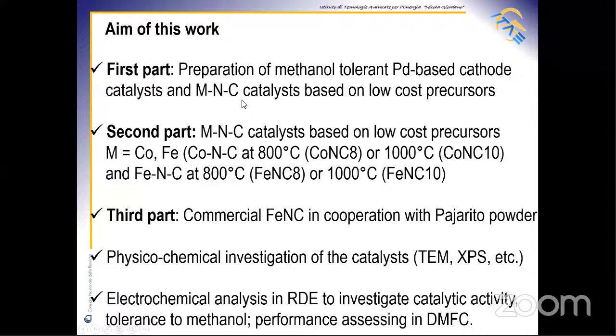So this work is divided into three parts. In the first part, we talk about the preparation of methanol tolerant palladium-based cathode catalyst. In the second part, we talk about the metal-nitrogen-carbon catalyst based on low cost precursors. The metal in this case is either cobalt or iron, and it was treated at two different temperatures, 800 degrees centigrade or 1000 degrees centigrade. We called these catalysts CoNC8, CoNC10, FeNC8, and FeNC10, but the numbers refer to the heat treatment and not to a stoichiometry of the carbon.